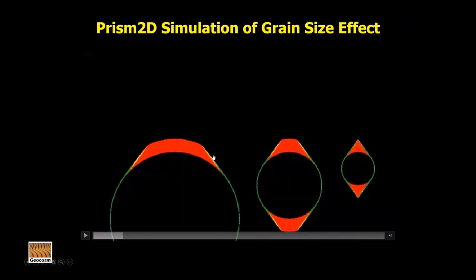Notice that these euhedral faces all have the same orientation irrespective of the size of the crystal. And because of the smaller area we're growing here, we achieve that euhedral termination with less distance along the c-axis for the small crystal compared to this big one. And so the effect here is that we have no surfaces anymore where we're growing rapidly on non-euhedral surfaces for this grain. On the other hand, this larger grain, we have this entire surface right here that is growing at a fast rate. And so the net rate of growth, the average rate of growth, is going to be faster per unit surface area on this larger grain compared to the smaller one. So I hope that makes sense for why that would be the case.